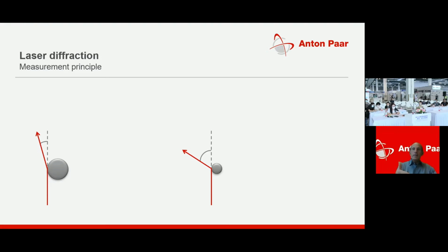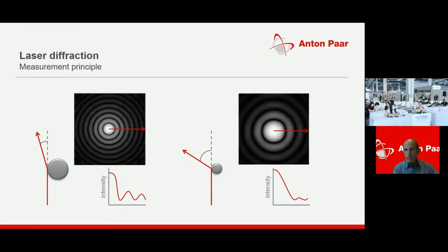Just briefly, the laser diffraction method for particle size analysis is based on the principle that the diffraction angle depends very strongly on the particle size. Larger particles provoke a smaller angle of diffraction, while smaller particles show a larger angle of diffraction. For an assembly of particles, we obtain a diffraction pattern with a specific intensity distribution and use an appropriate model that we apply to convert this diffraction pattern into a final particle size distribution.